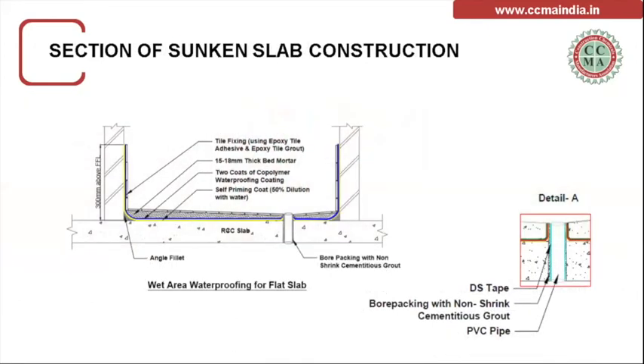This is the brief sectional picture that we have put. This is what we were mentioning. We can go straight away with the tiles, even on the vertical surface as well as the horizontal. It doesn't require a protective screed like how we design for the acrylic cementitious coating. And for detailing, yes, the devil is in the detail for the sunken slab. We have to make sure that we use bore packing with non-shrink free flow material. Then we have to use gap seal tapes on the pipe so that different kinds of material do not give way at the sleeve gaps, which may be the source of leakage. This is the detailing we have to take care of specifically when we do wet areas waterproofing.